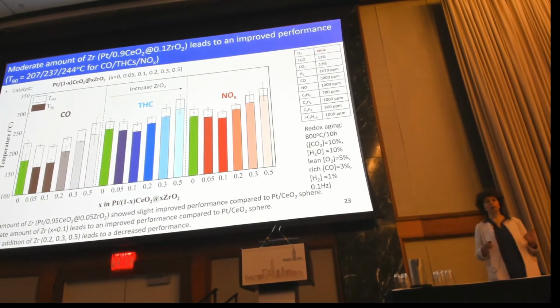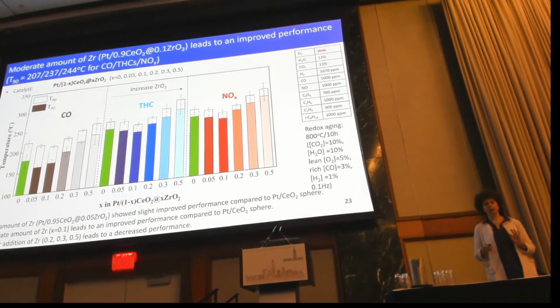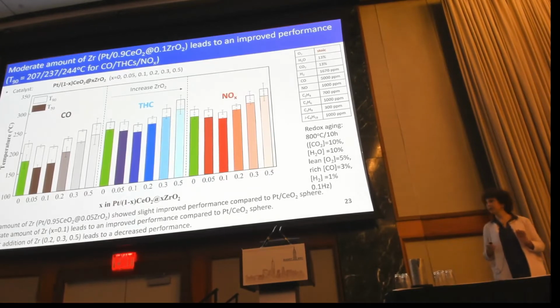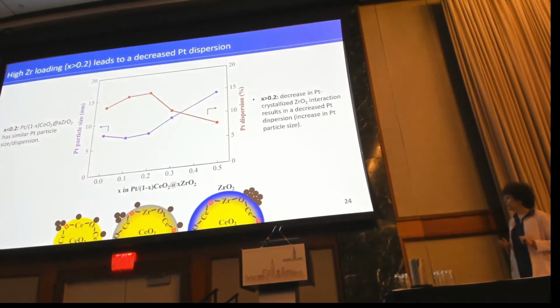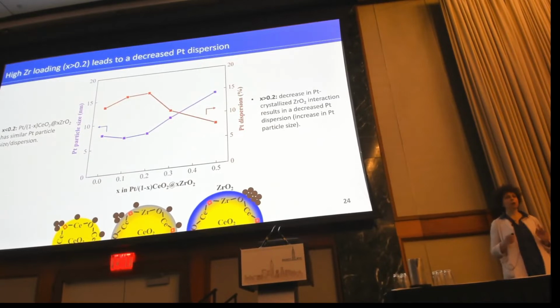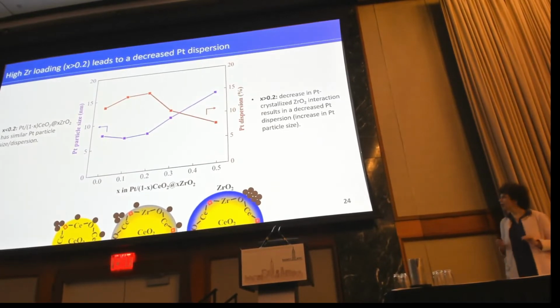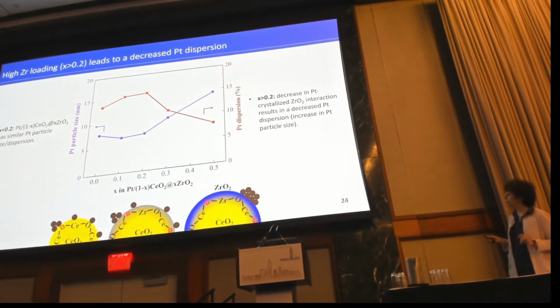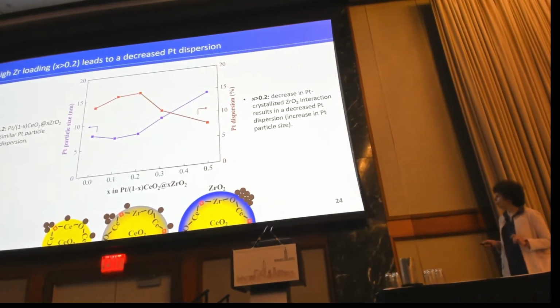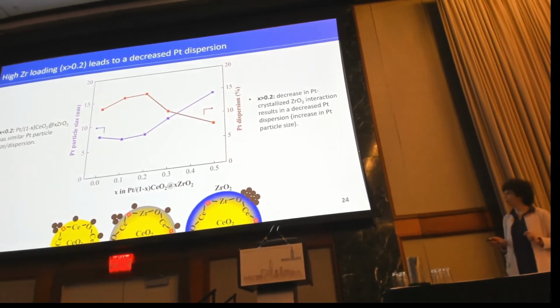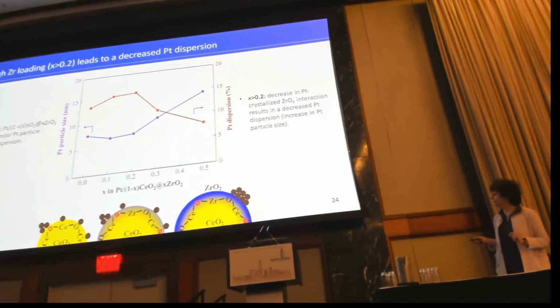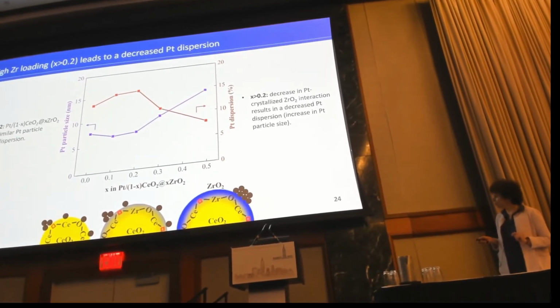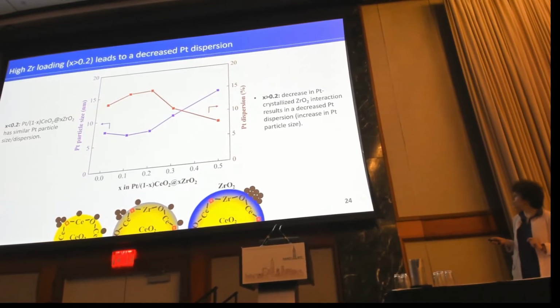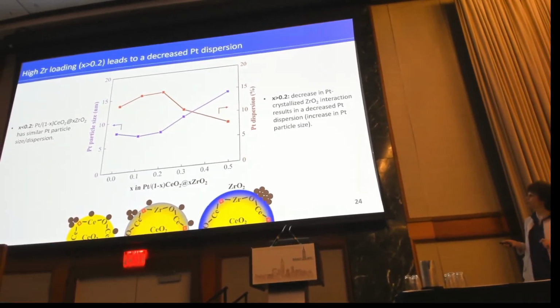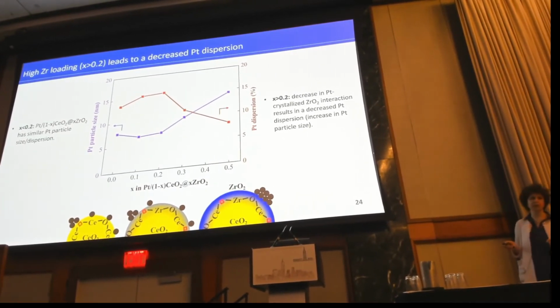So at this point, we want to understand what is the effect of the zirconium on the platinum particle size, and for this reason, Judy did CO chemisorption experiments where she was able to find the platinum particle size as well as the platinum dispersion in this series of materials as we were changing the zirconium content. What we see is that when the zirconium content is up to 0.2, the platinum particle size is pretty much the same.